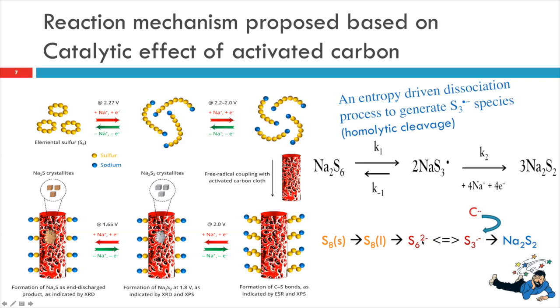And what we have proposed in this paper is that this S6 minus goes through disproportionation reactions, because we are using a highly aprotic solvent with a high donor number, and that is facilitating this S6 minus going to S3 monoanion, the mono radicals. So that formation, we think, is an entropy driven process, and it is forming on a very fast scale.